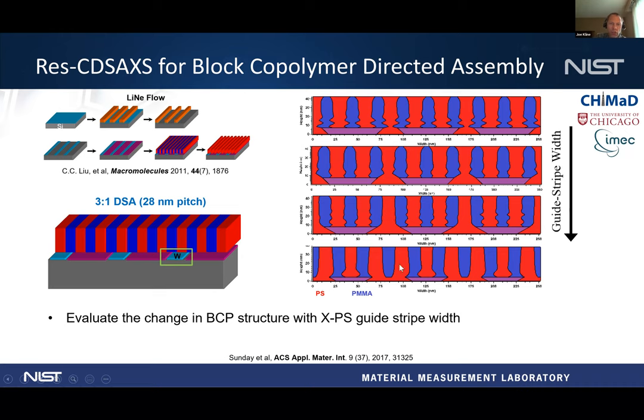And so between this third one and the fourth one, you actually can't get the epitaxial alignment to work. And then once you get big enough, you get a shift where it's now centered with PMMA on top of the polystyrene instead of the polystyrene being on top of the PMMA.